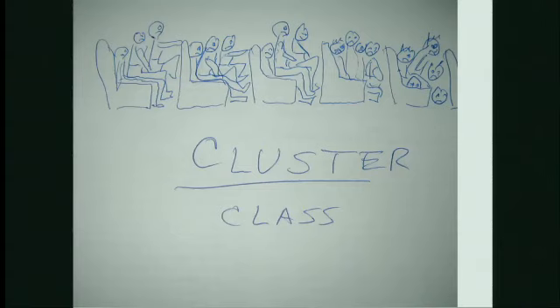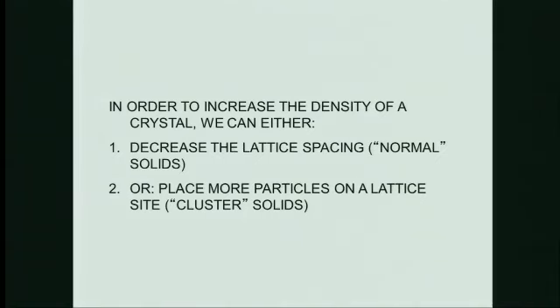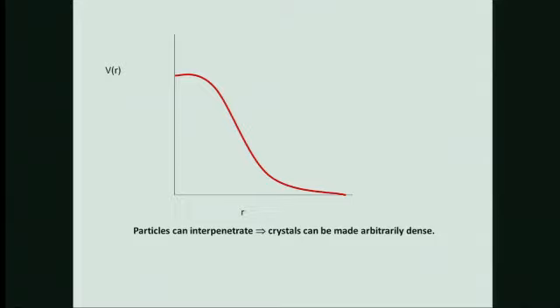Now, this is precisely what happens if you take particles with a soft interaction. So you can do two things to increase the density of a crystal. Either you decrease the lattice spacing, or you put more particles on a single site. And this, for instance, happens if you have a potential like this. This is a repulsive potential. It is bounded, so it doesn't go to infinity at 0. And importantly, another condition is that it should have a Fourier transform that has a negative part. So it can't be a Gaussian, but if it's a bit flatter than a Gaussian, like e to the power minus x to the power 4 or something, then it can form a cluster solid.